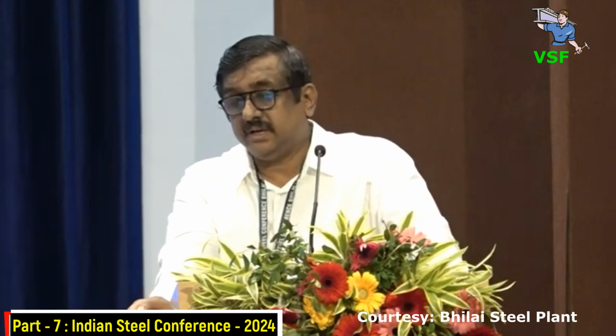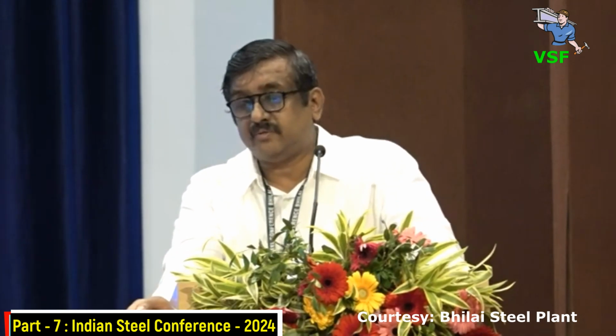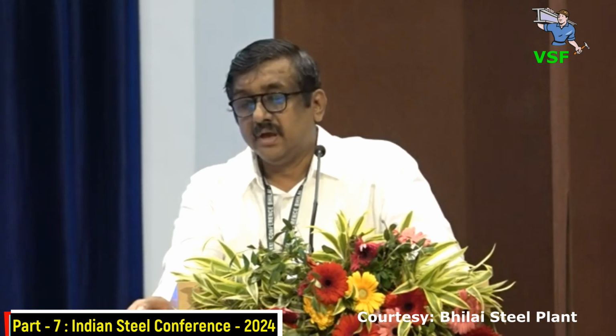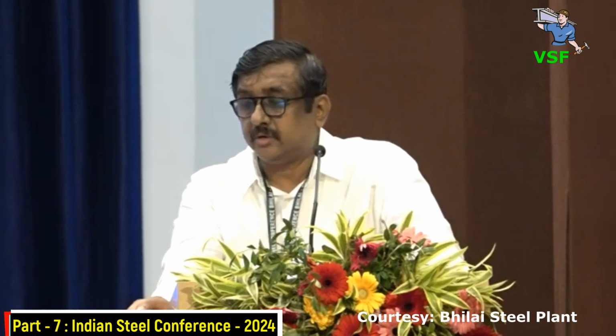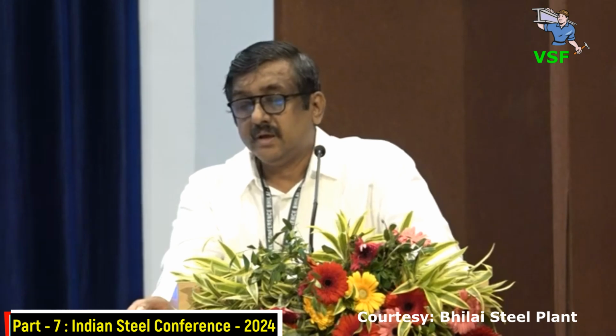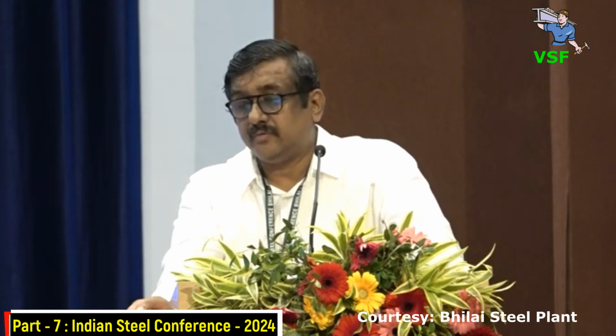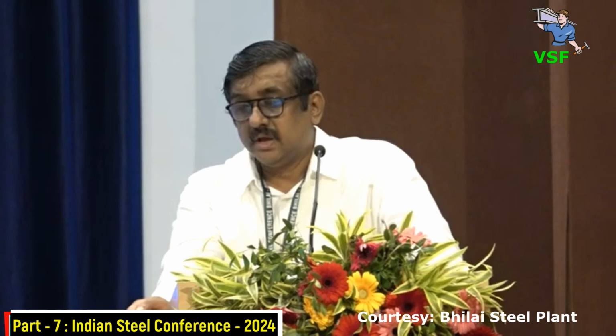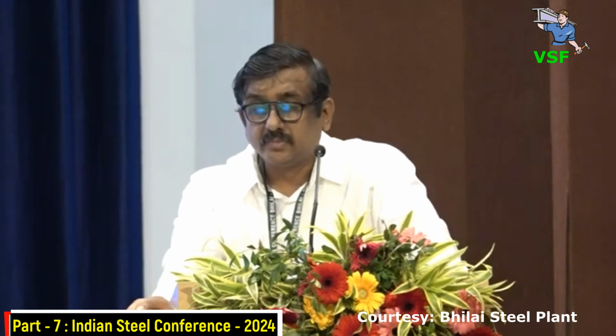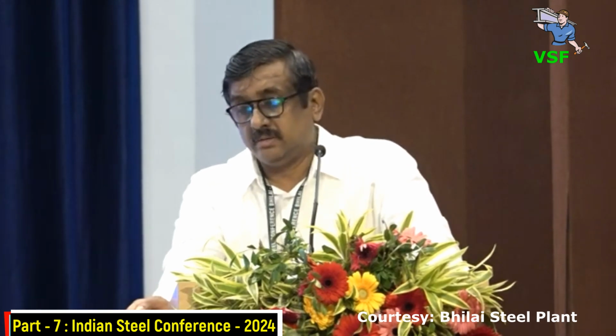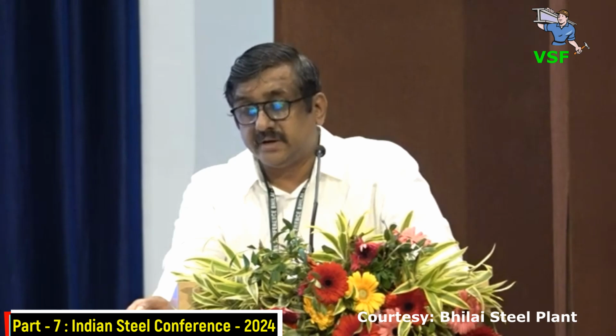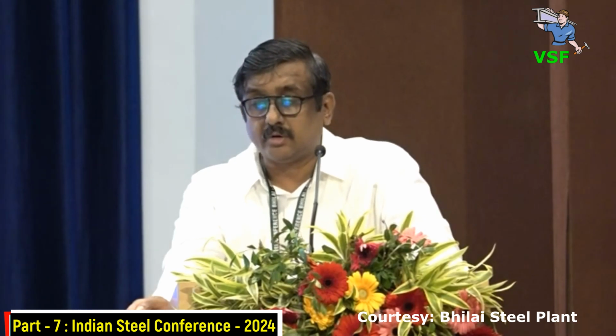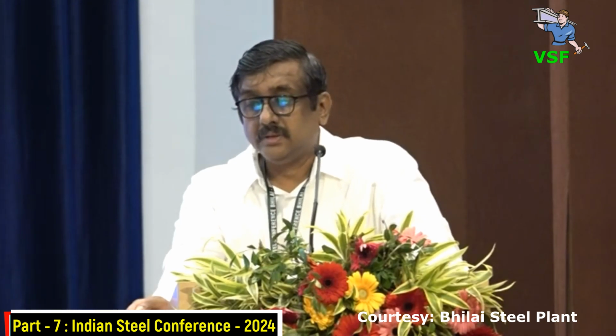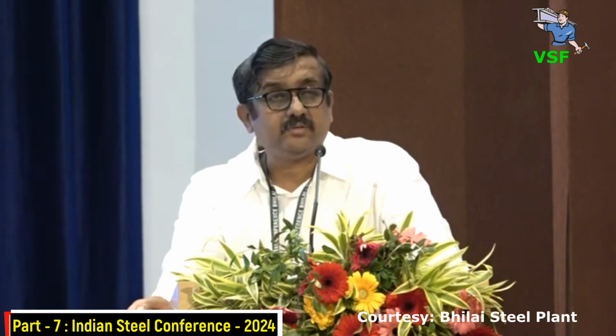The results are: heat recovery of 1.5 gigacalories per hour, reduction in coke breeze consumption of around 2 kg per ton, expected reduction of CO2 of 5,000 tons per year, and improvement in productivity by 2.7%. The other benefits include improvement in tumbler index by 1%, the sinter quality. These are the main benefits of the system.